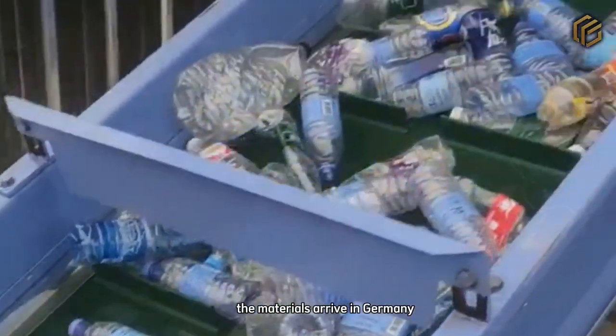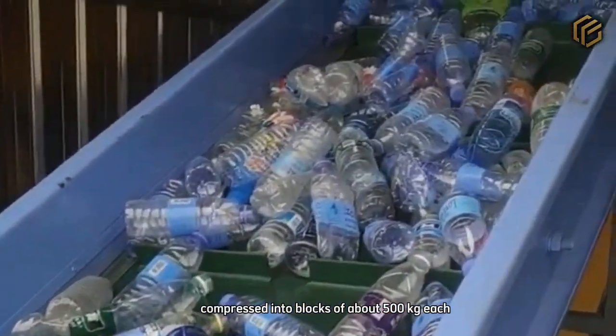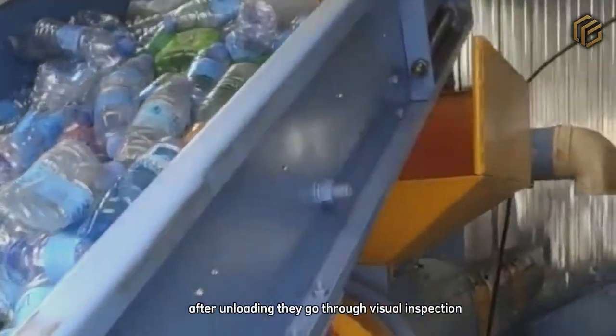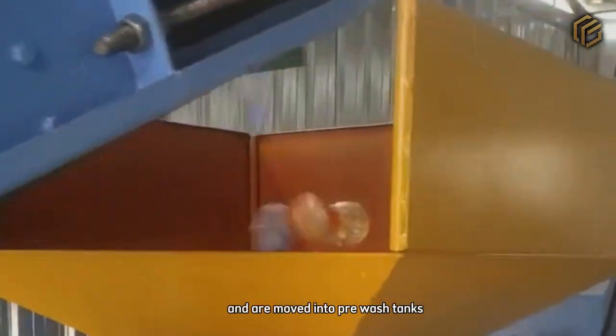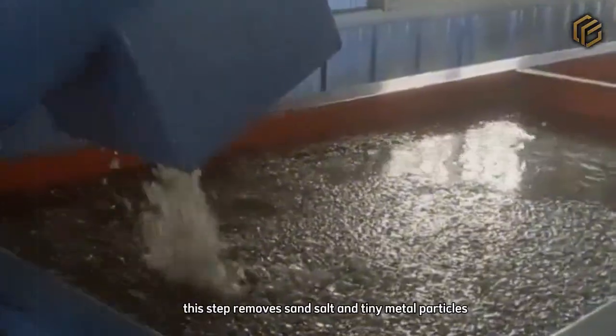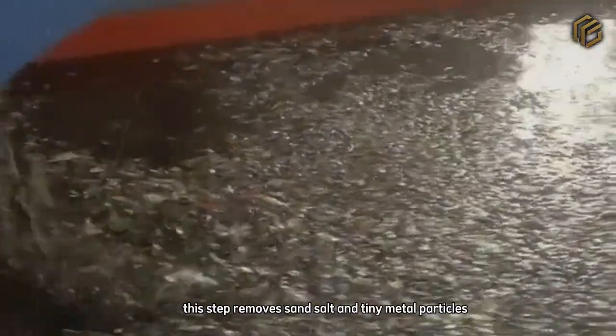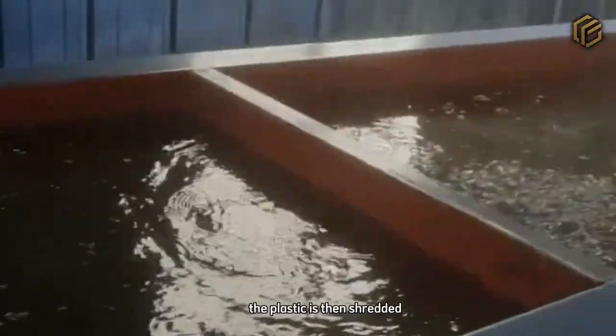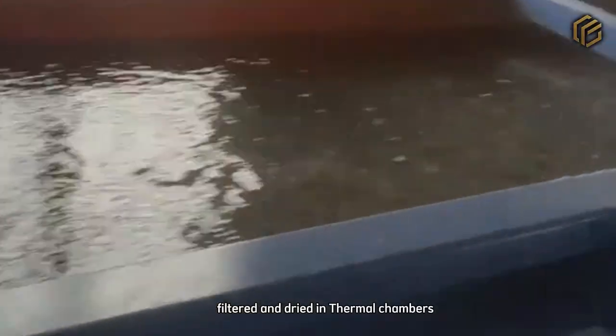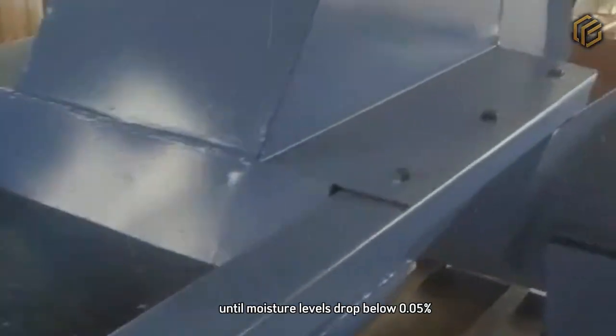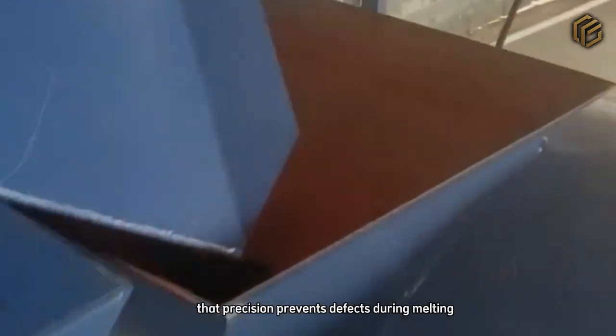The materials arrive in Germany compressed into blocks of about 500 kilograms each. After unloading, they go through visual inspection and are moved into pre-wash tanks. This step removes sand, salt, and tiny metal particles. The plastic is then shredded, filtered, and dried in thermal chambers until moisture levels drop below 0.05%. That precision prevents defects during melting and yarn extrusion.